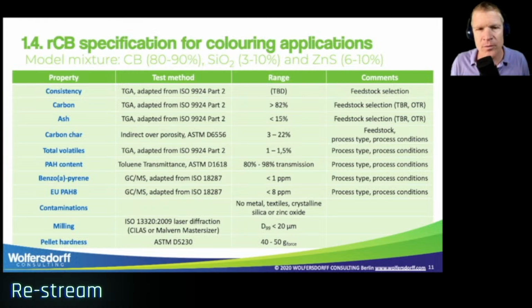Now, the most important property is the consistency. At this time, there is no confirmed testing method from ASTM. You might know ASTM has a workgroup D24 that is working on norms and specifications for recovered carbon black. So at the moment, the exact specification of the consistency is pending. However, in my opinion, consistency should start with a consistent TGA result.